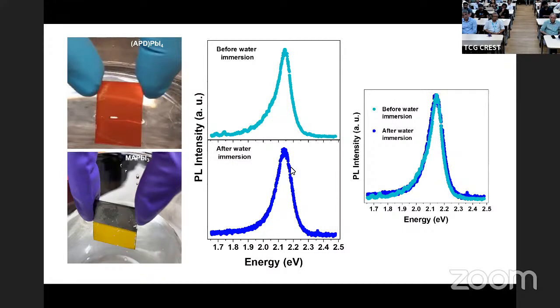It turns out that the best stability that was reported in the literature before, in a JACS paper in 2018 or 19, where they said that they can dump the crystals into water and it takes 15 minutes before it begins to form PbI2. When we dump this into the water, it takes more than 4 hours before it begins to show PbI2. So it's extraordinarily stable.